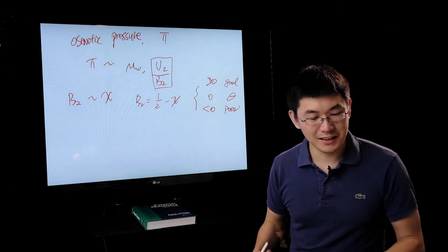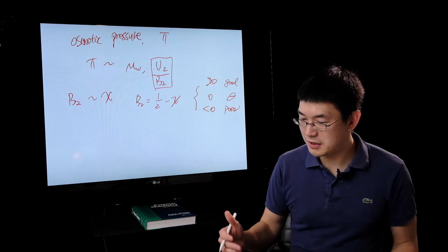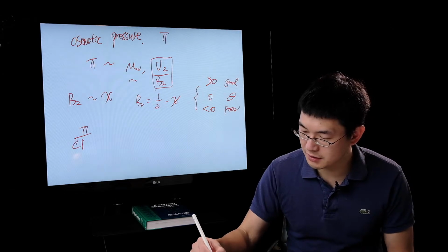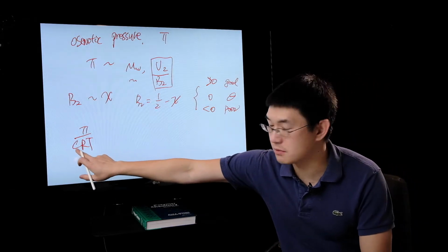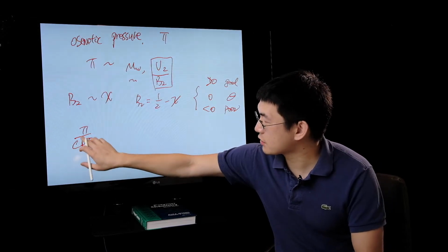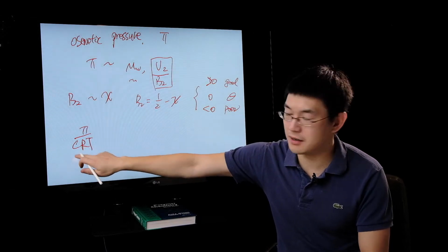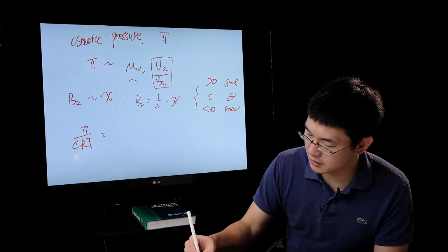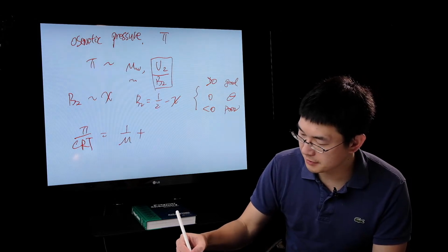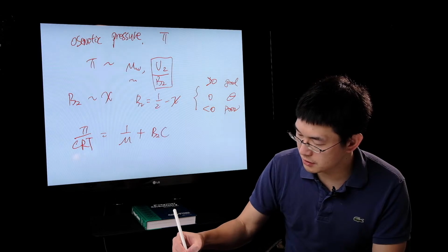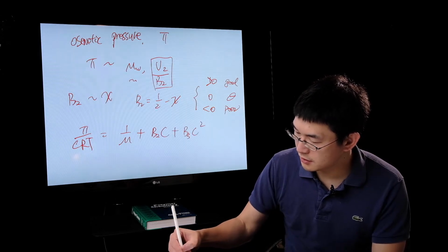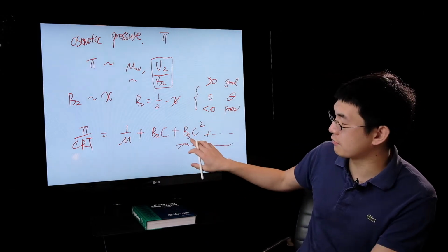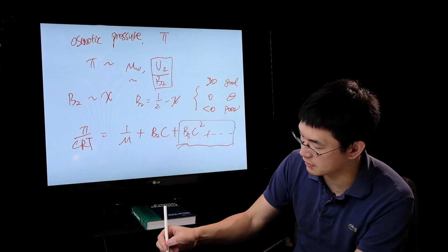And we know that there's another great use for this, which is to get the molecular weight. If you measure osmotic pressure and plot it divided by concentration, please be careful, you actually have to divide the osmotic pressure by cRT, then you can get a linear relationship with the B2 term, and there's a higher order term. Actually, we usually don't even consider the third virial coefficient term, so this is usually eliminated.